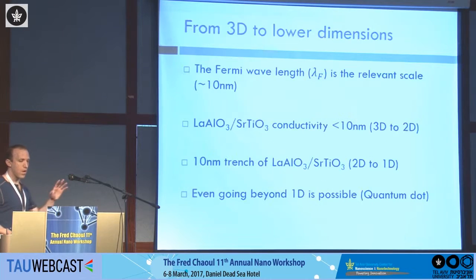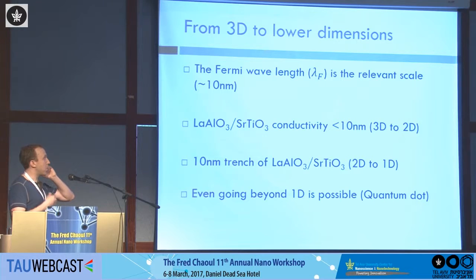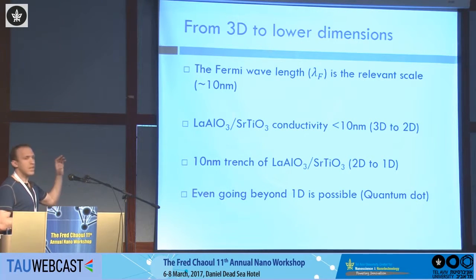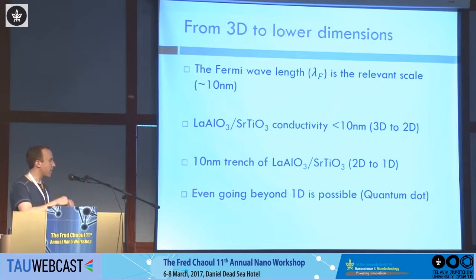So we have the material, and now we just need to go from 3 dimensions to 0 dimensions. As I said before, the relevant length scale is the Fermi wavelength, which depends on the Fermi energy of this material. In our material, it's 10 nanometers, really small. From 3 dimensions to 2 dimensions is really simple because this material is already 2 dimensional. A lot of studies already show that the conductivity is under 10 nanometers. If you want to go to 1 dimension, it's really easy. Actually, it's not really easy at all. You create a 10 nanometer trench. And even going beyond 1D is possible, and I'll show you this in a minute.